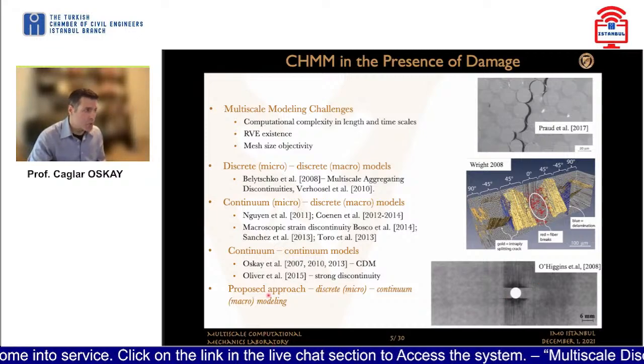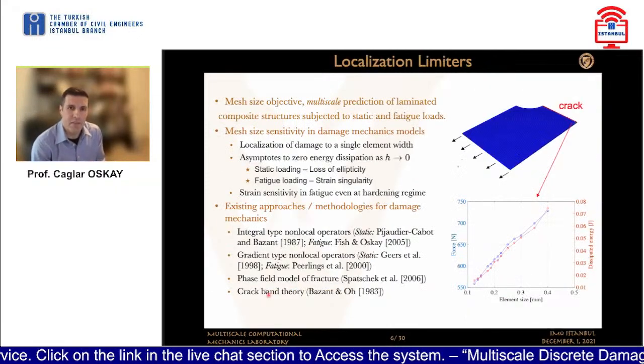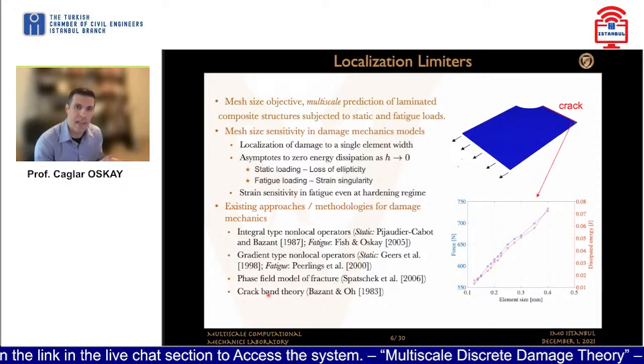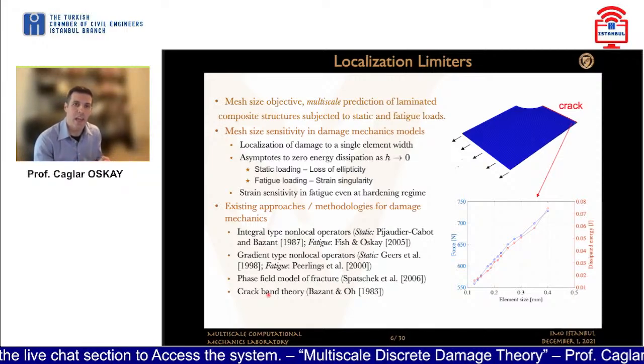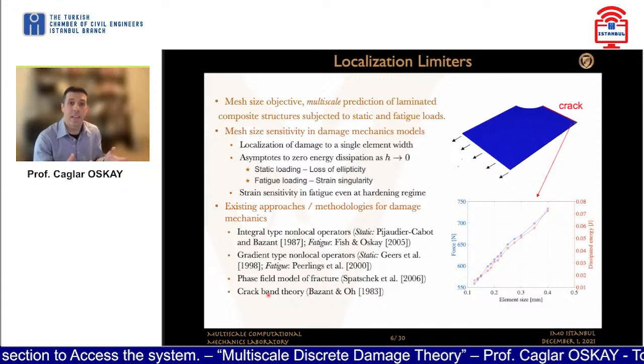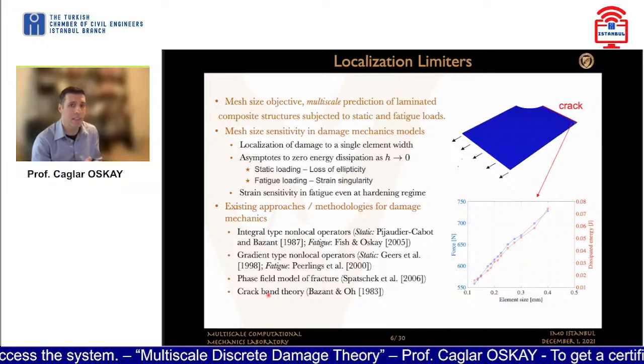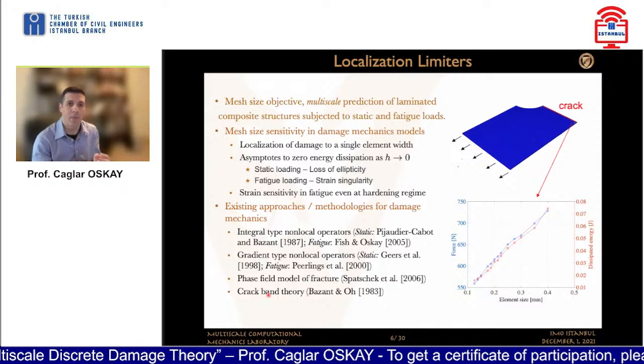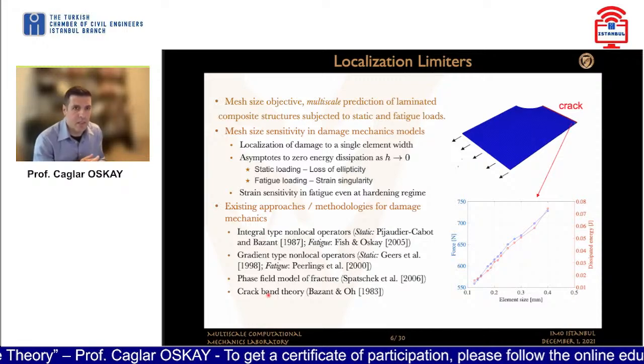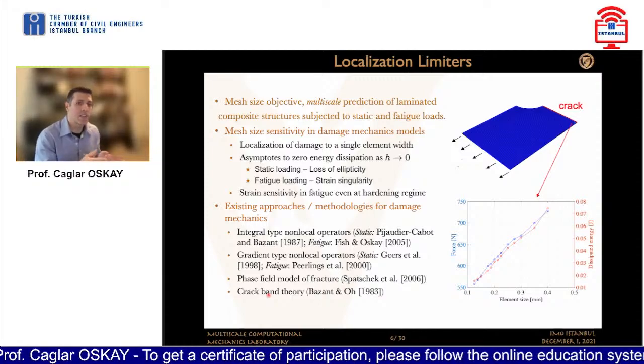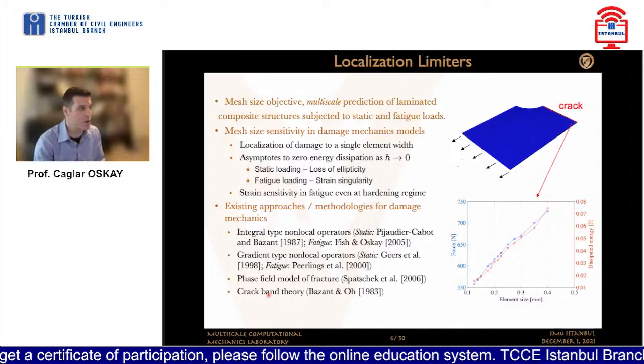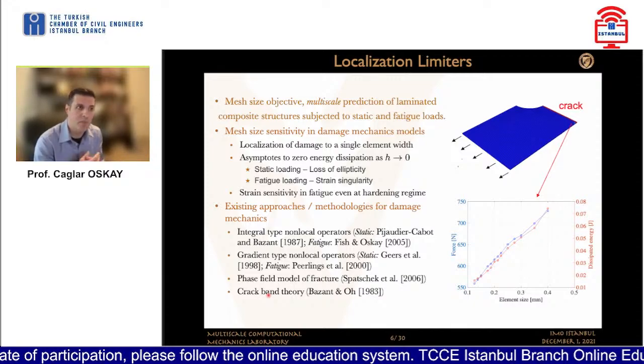The next issue, as I mentioned before, is this issue of mesh size sensitivity. Naturally, when you do a computational analysis, there will be an effect of how densely you discretize your system to solve, and the accuracy will be affected by that. But what we're talking about here is something a little bit different. What we call mesh size sensitivity in damage mechanics models refers to the localization of damage to a single element width, if you're using finite element analysis, for example, regardless of the size of the finite elements. Now, this does not necessarily constitute a problem by itself, but what happens is that as you refine the mesh, the amount of energy dissipated during the fracture process also asymptotes to zero as the mesh size asymptotes to zero. That's a problem because you basically are not dissipating any energy because of the fracture process. And so this is a common and traditional problem.